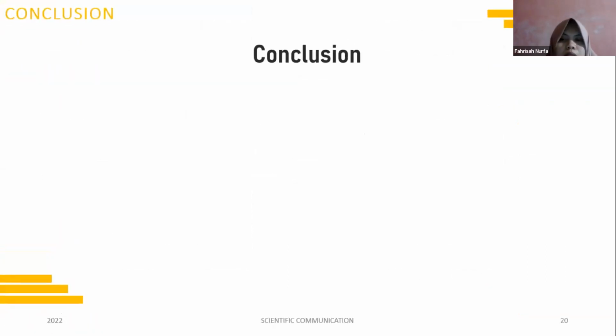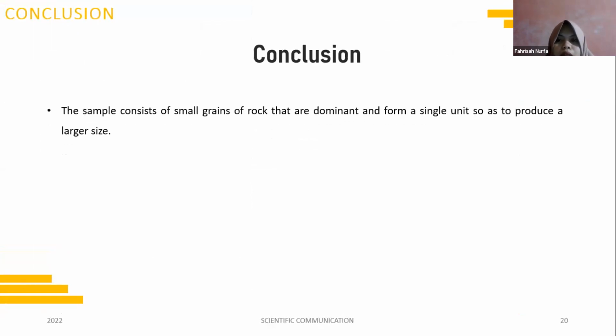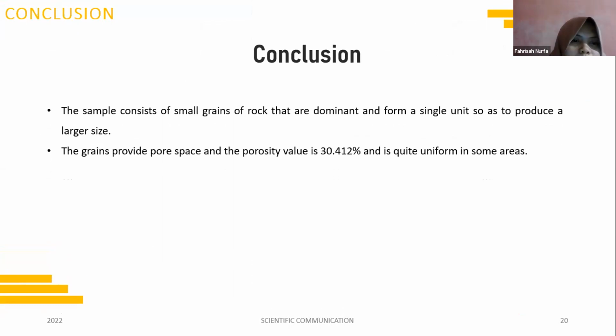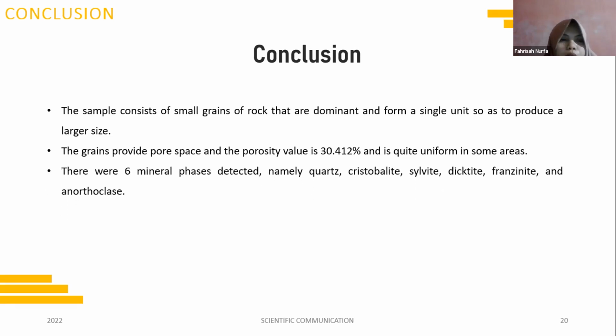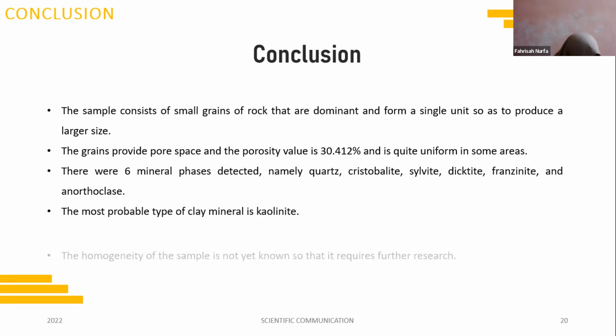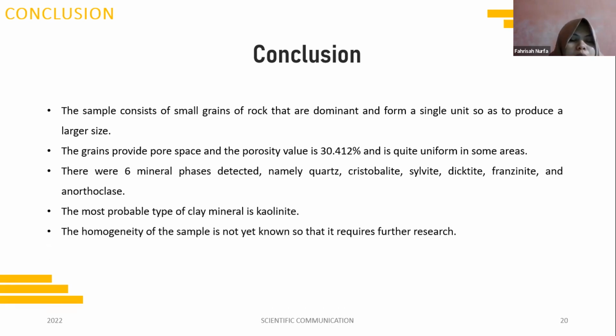The last is the conclusion. We know that the sample consists of small grains of rocks that are dominant and form a single unit so as to produce a larger size. The grains provide pore space and the porosity value is 30.412% and is quite uniform in some areas. There were 6 mineral phases detected, namely quartz, cristobalite, sylvite, dicktite, franzinite, and anorthoclase. The most probable type of clay mineral is kaolinite, and the homogeneity of the sample is not yet known, so it requires further research.